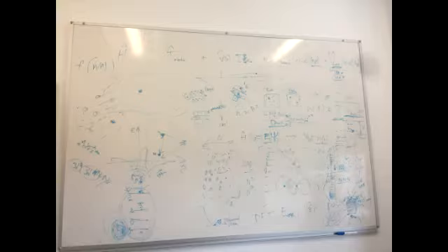temporarily, and this dipole will interact with the next dipole. It's a super weak interaction, but it's super important in organic systems, for example. In our case, maybe not so much. So you should know that if you calculate these two benzene rings with LDA, you will get some van der Waals interaction. If you calculate with GGA, you won't see any van der Waals interaction. So again, depending on your system, you need to adjust which one you want to use.